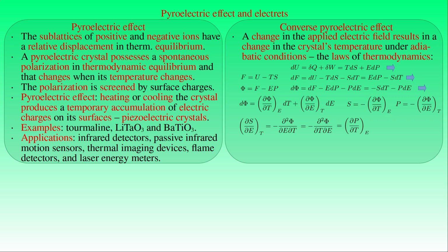This result is a Maxwell relation between the entropy and the polarization of the pyroelectric crystal, where the partial derivative of the polarization P with respect to the temperature T at a constant field strength E in the right-hand side of the relation is defined as the pyroelectric coefficient p of the crystal. The latter describes the pyroelectric effect in the crystal since p is the constant of proportionality for the pyroelectric current through a given electrode area generated by the change in the temperature of the crystal.